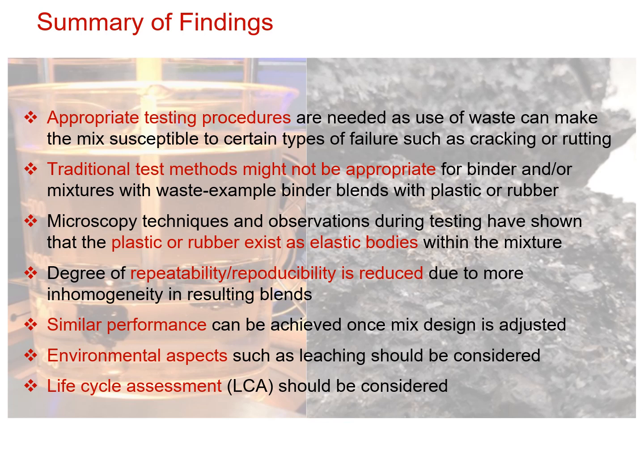We have seen also that traditional test methods might not be appropriate when we have waste in the materials. In case of plastic or rubber, for example, the softening point temperature, we got very funny results there. And when we used also microscopy techniques, we could see that the plastics or the rubbers are still existing as elastic bodies within our mixture. So as our material becomes softer with temperature, then these elastic bodies help in performance of the material.